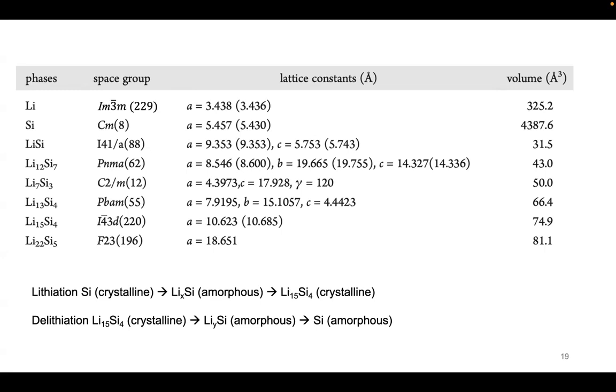Now, when you move to nanostructured silicon, what's interesting is you now have kinetic issues to deal with. And what is observed actually is that there is a formation during lithiation. When you start off even with crystalline nanostructured silicon, you form an intermediate lithiated silicon phase that's amorphous. And that results in the formation of this metastable Li15Si4 crystalline phase. And you can see that in situ, and this has been established for about 9 years now, well, actually more than that if you include the ex situ characterization work from 2007 from Obrovac. So the fact that it's nanostructured means there's a different pathway than just going from crystalline silicon to the crystalline compound, but it